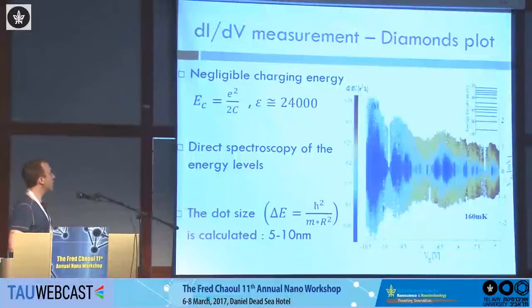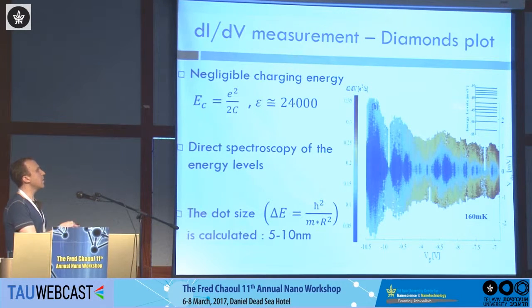Another issue I want to discuss is, if you remember the Coulomb interaction and charging energy, in our system the charging energy is negligible, because the dielectric constant is huge in STO, and because of this, we don't have to rely on it at all. What it actually means is that we have a direct spectroscopy of the energy levels, because we don't have to take into account this charging energy. And by that, we can just count the spacing between those Coulomb peaks and calculate, as you can see here, the energy spectrum. And from that energy spectrum, we can estimate the size of this dot, which is 5 to 10 nanometers, and it's self-consistent with the Fermi wavelength under 10 nanometers.